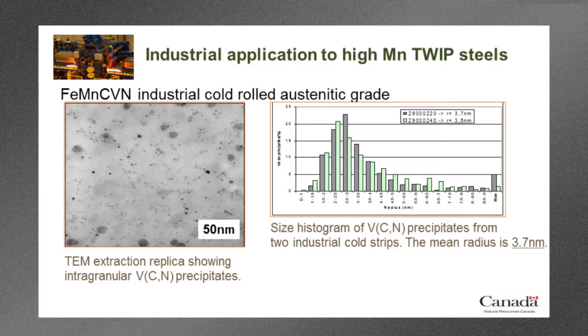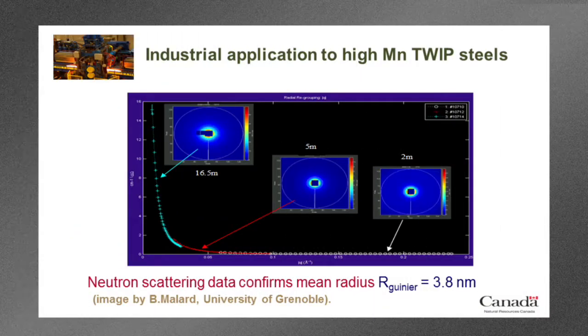This is the size histogram measured at various points on two industrial coils. So these are actually industrial data. The two different colors represent two coils, with very similar behavior. What we see is that the mean precipitate radius is very small, only 3.7 nanometers. So we would expect a very good strengthening effect from those precipitates in this type of steel. We actually confirmed that, because the problem with TEM data is there's always an argument: is it representative of such a very small volume that you're analyzing?